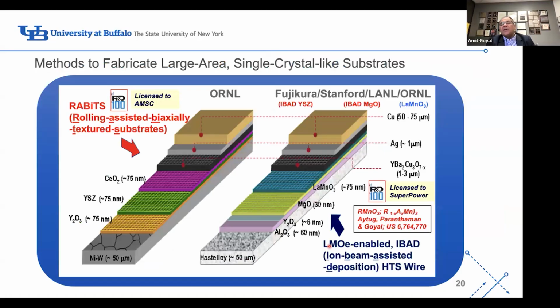So two processes are being used around the world now to manufacture long lengths of high temperature, high performance superconducting wire. The first is the rolling assisted biaxially textured substrates. This is something we invented at the Oak Ridge National Laboratory. We call this like an aluminum foil process, much like the aluminum foil you have in your kitchen sink. We just create it out of a different material. We make it such that all the atoms are aligned in all 3 directions. Then we deposit ceramic materials, which we call buffer layers, on top of them in nanoscale. Then we deposit the superconductor. All of these have the same atomic structure and configuration, which is like a single crystal. Then we deposit some contact layers and then a copper stabilizer layer.